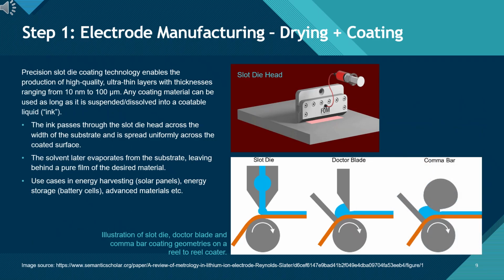Electrode manufacturing, drying plus coating, slot die technology. Here we see the precision coating tools used in electrode production. The first picture shows a slot die head, which is today's leading technology for battery coating. In this method, the slurry, sometimes called ink, is pushed through a narrow slot across the foil. This ensures a very uniform layer, with thickness controlled down to just a few microns. Slot die coating can make layers from as thin as 10 nanometers to over 100 micrometers, depending on the process.